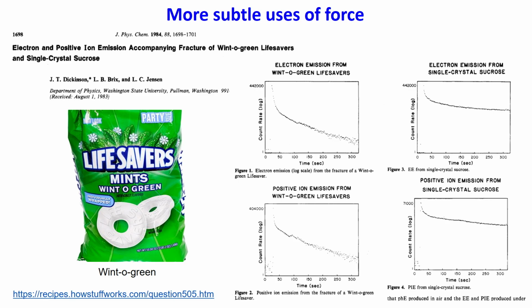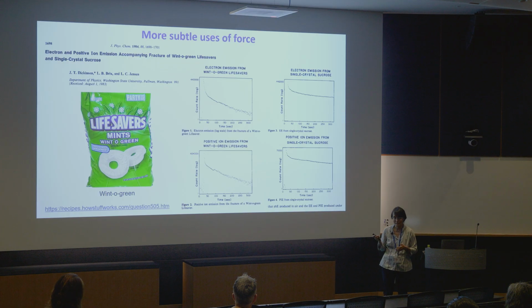And a different implementation of this phenomenon is through the use of this particular type of candies called wintergreen. So they contain a wintergreen oil, which is fluorescent. And when you crack those candies with pliers, for example, you can also see emission of light, but that is a bit easier to see because it's activating also the fluorescent oil present in it. And actually, this is a very complicated phenomenon. As it turns out, it's accompanied by emission of electrons, the positive ions, and even radio waves.